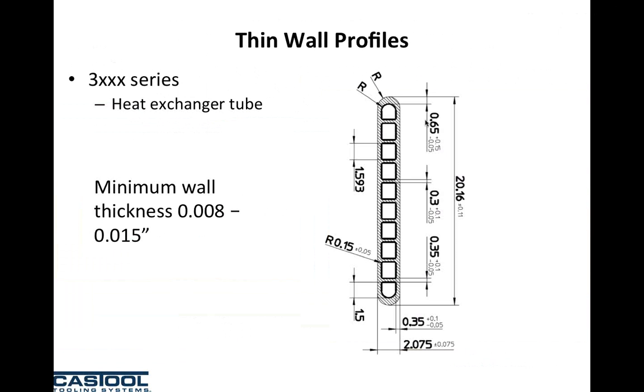If you want to do heat exchanger tubing or precision tubing, where your wall thicknesses can get down to 8 to 10 thou and are often less than 15 thou, the reality is the flow stress of 6063 alloy does not enable you to extrude that thin of a wall. Basically, the die would plug and nothing would come out the other end. So we go to alloys with lower flow stress that can also extrude thinner walls.